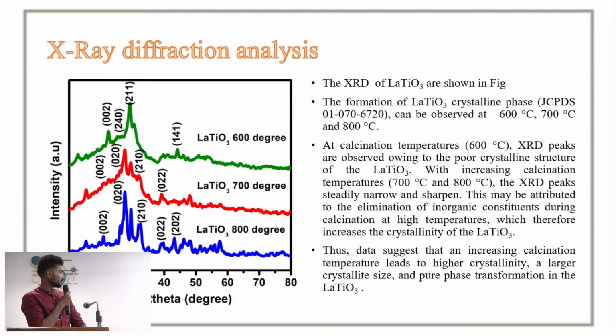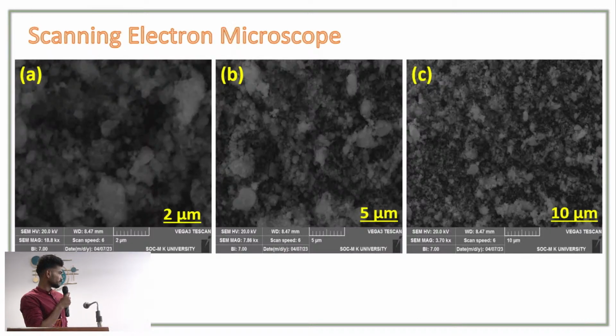In my XRD analysis, we can see three different calcination temperatures, where green represents 600 degrees Celsius, red represents 700 degrees Celsius, and blue represents 800 degrees Celsius. At 600 degrees Celsius, the XRD peaks show a poor crystalline structure of lanthanum titanate. When increasing the calcination temperature to 700 and 800, the XRD peaks steadily narrow and sharpen. This may be attributed to the elimination of inorganic constituents during calcination, which increases the crystallinity of lanthanum titanate. Thus, the data suggests that increasing calcination temperature leads to higher crystallinity, larger crystalline size, and pure phase transformation in lanthanum titanate.